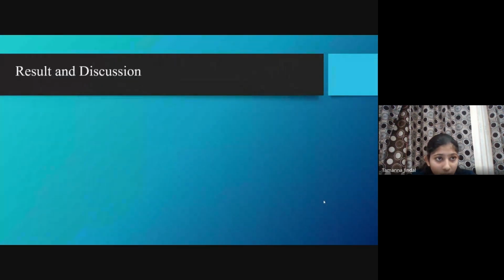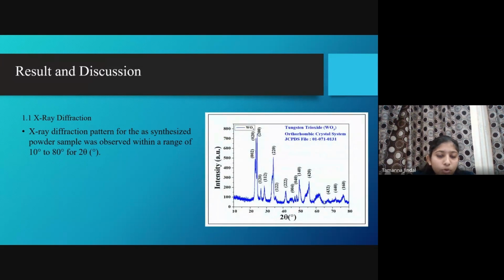Finally, I'll move to the results and discussion. Firstly, X-ray diffraction. The X-ray diffraction pattern for the synthesized powder sample was observed within a range of 10 degrees to 80 degrees for the 2 theta position. The Debye-Scherrer formula is often used to determine the crystallite size, as we all know. And the crystallite size of the WO3 tungsten oxide was approximately 23 nanometers.